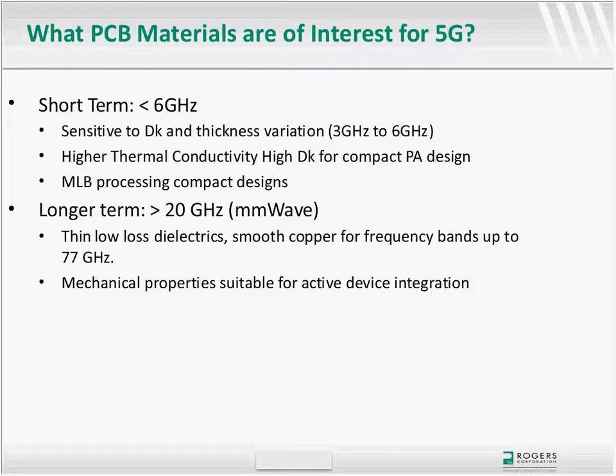In the higher frequency bands, millimeter wave, we tend to see the need for thinner dielectrics and smooth copper foils in order to reduce losses at the higher frequencies, which becomes more and more important. Low dielectric constant values are also an important factor. On mechanical properties, we're starting to see more and more device integration, surface mount on many of these devices. So the processing and mechanical properties more commonly found in digital boards, which have a lot of this integration, are also important for the designs.